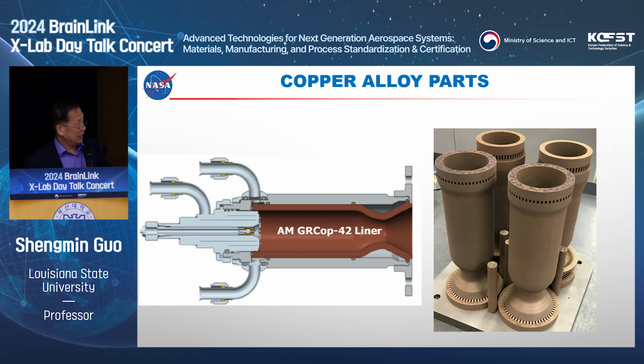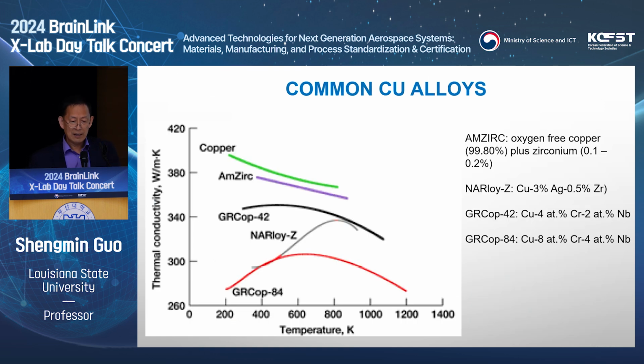They printed out this rocket engine nozzle, actually fire tested. Look at the properties of the copper alloys. You may say, look, that's the conductivity against the working temperature. My contribution in that book published by NASA is to obtain all those thermal properties of AM parts working over different temperature ranges. So look at the pure copper.